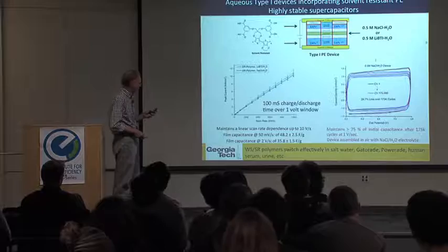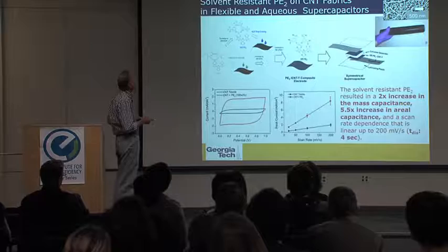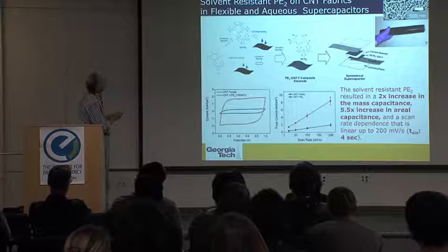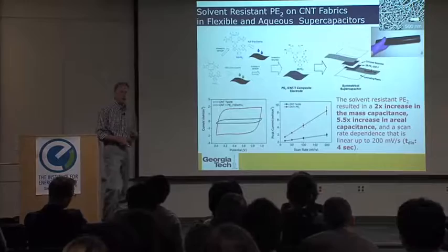Now if we take those water-soluble polymers and want to deposit them onto the carbon textile, again, here's an electron micrograph of that carbon textile, and there's a roll of the carbon textile material. We can embed the polymer into the textile by, for example, casting the polymer onto the textile and then saponifying inside the textile, or first forming the water-soluble polymer and imbibing it into the textile. We find the bottom route is actually better due to the hydrophobicity of the textile itself.